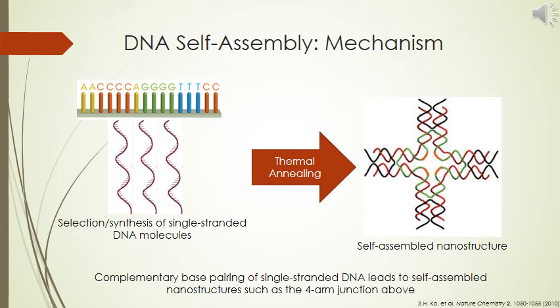Given the nature of complementary base pairing, the mechanism of DNA self-assembly is relatively straightforward. The DNA self-assembly process begins with careful selection or synthesis of single-stranded DNA molecules. These single-stranded DNA molecules are then placed in aqueous solution and annealed at an elevated temperature before being slowly cooled.